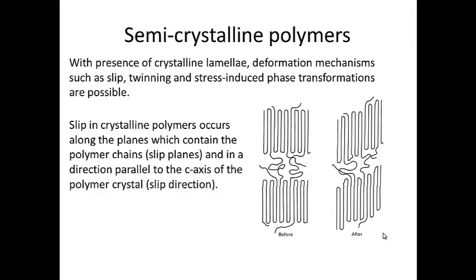Generally speaking, what happens in semicrystalline polymers is that first, you orient the amorphous regions of the chains and straighten them along the direction of the tensile axis. In the next step, the crystalline planes slip and align themselves in a shear orientation with the applied stress. You can see here that the planes of the crystalline region are being sheared in order to allow deformation in the vertical direction, and that shear occurs parallel to the c-axis of the crystalline structure, the unit cell.